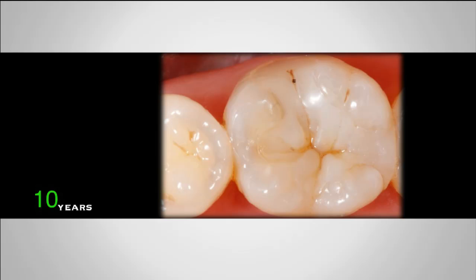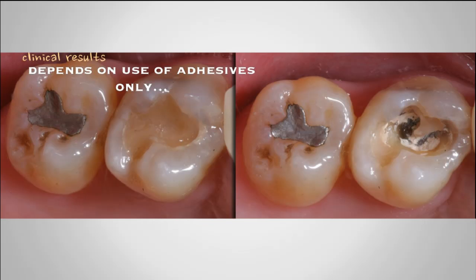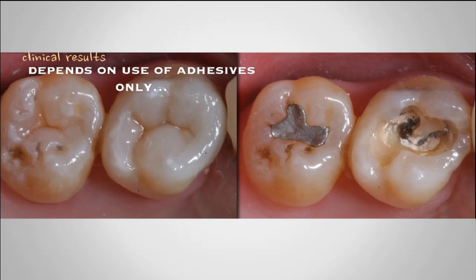10 years after, I can see some staining on some parts of the composite. The interface is still sealed, and I don't need any repair. Okay, but I have to understand that all the results of composite depend on the adhesives themselves. I can use composite, but it's better for me to use composite only with adhesive, without any base. That means without a glass ionomer as an interface or without calcium hydroxide as an interface. It's always better to use composite only with adhesive layers, and this is something that we have to accept.